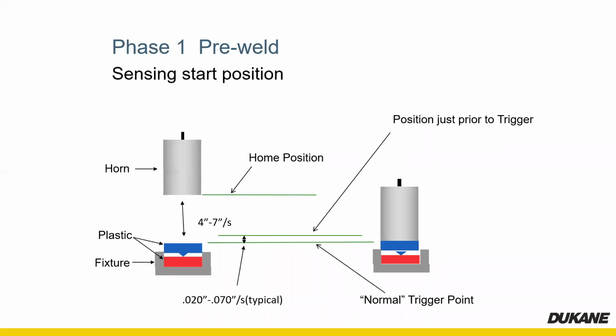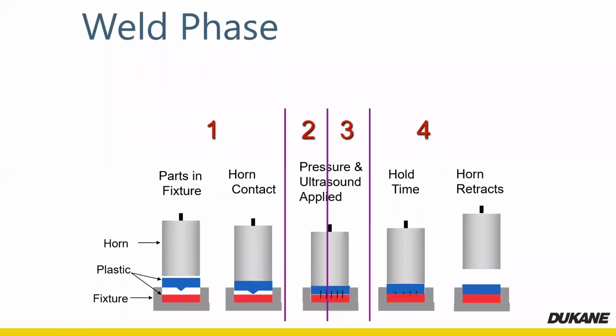So we come down very quickly and then slow down so that we're very consistently and gently building up that trigger force, so our position at trigger becomes a very repeatable and known number, essentially within the tolerance of your plastic. If your plastic has a height tolerance of ±2 on each part, then when you look at the data, your position at trigger should be within that 4 thousandths window. You don't have any bouncing or inconsistencies like you see with pneumatic welding. So again, we're starting from a very known, very consistent point, and going from there.